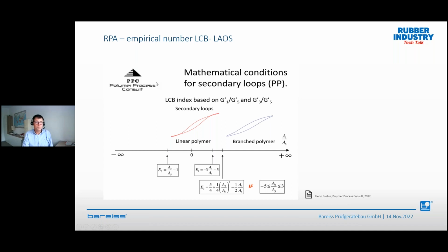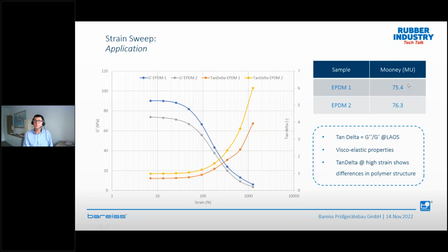So on our example, I would like to show again, remember both EPDMs have the same Mooney viscosity. And when we plot on the left side, you see G prime, the blue one and the gray one, G prime as a function of strain. And the yellow one and the orange one is tan delta as a function of strain. And you see at a very high strain, a huge difference in tan delta. Remember, tan delta is the ratio between G double prime and G prime and gives you information about viscoelastic properties. So here we have the second one.